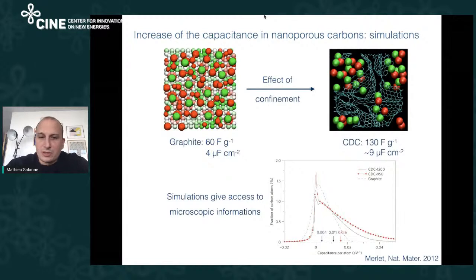The first thing we did was to look at the local charge on the carbon atoms. And this is what you have here at the bottom. You have the distribution of charge in graphite, which is given by the dashed line, and you have two examples of nanoporous carbon. And you see that this distribution is very different. In fact, in the case of graphite, even if the electrode is positive, you still have some negative charges at some point. While in the nanoporous carbon, most of the carbons are positive and some of them are very positive. You have this very skewed distribution. And this means that some carbons are really important, more important than others in the charge storage.